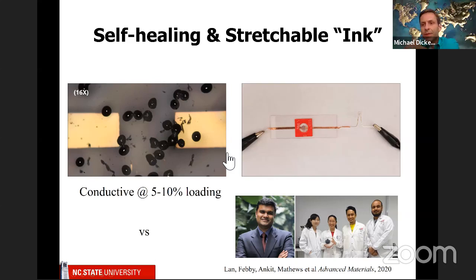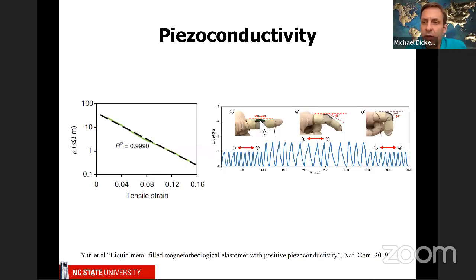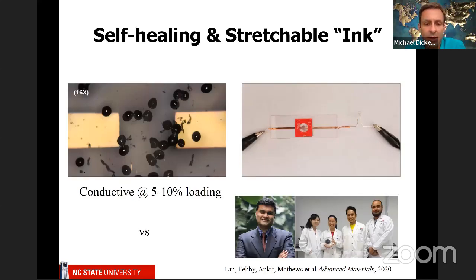Now, in this prior work, and I don't know why my little graphic is not showing up here, but in this prior work that I've shown, these sort of composites are highly loaded with liquid metal. They've got something like 80, 90% filler. And so one of the things that we've actually done, this paper just came out this week, was this work with the collaboration from some really amazing students from Singapore, a couple of undergrads and a graduate student all working together. I'm shown here in this picture with Professor Matthews. So basically what we did is we took liquid metal particles and put them into silicone, but did not cure the silicone.